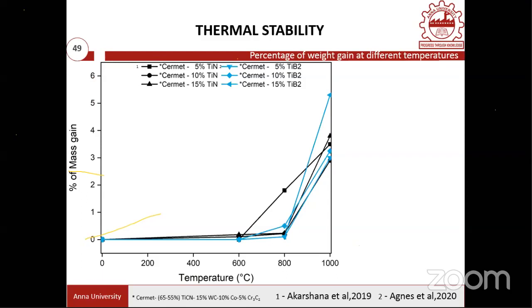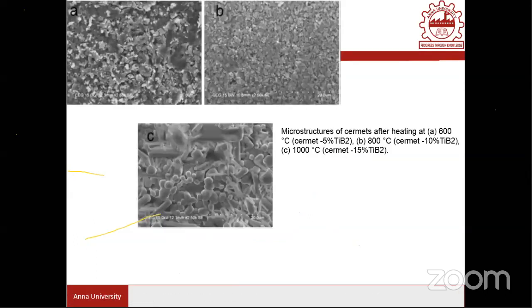And here, if you look at the bottom curve, which is the 5% TiB2 based CERMET, up to 800 degrees centigrade it's showing the least mass gain. That means up to 800 degrees centigrade, the stability is really commanding. But for all other cermets, at 1000 degrees centigrade, there is a mass gain. That means there is tremendous oxidation formation. And one can also see the grain growth at different heating temperatures.